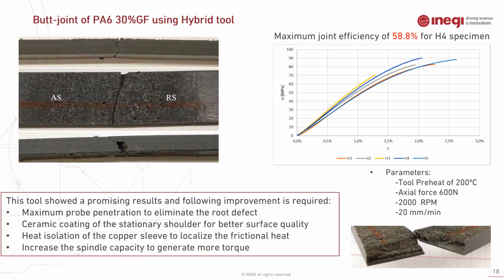First is the maximum probe penetration to eliminate the root defect, because as you can see on the right side, the probe could be longer to eliminate the root defect at the bottom of the weld. Also ceramic coating of the stationary shoulder for better surface quality, and also heat isolation of the copper sleeve to localize the frictional heat and not lose the heat for heating up the steel part, and we just have to be focused on the copper sleeve, and that can be done by isolating the heat. Also a better machine or increased spindle capacity to generate more torque is required to use this tool.